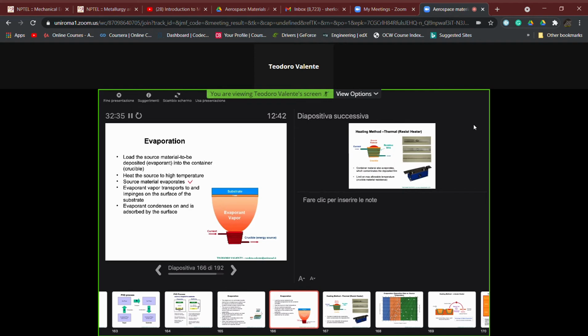and we have the evaporation phenomena. And this evaporation phenomena is able to establish an atmosphere which is rich in the elements which have been evaporated. And if you put the substrate in front of the crucible, for example, you can allow the condensation process and the fabrication of the film. So the evaporant condenses on the surface and is adsorbed by the surface. So it's a very simple mechanism.